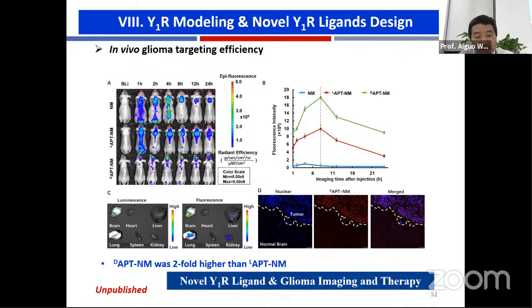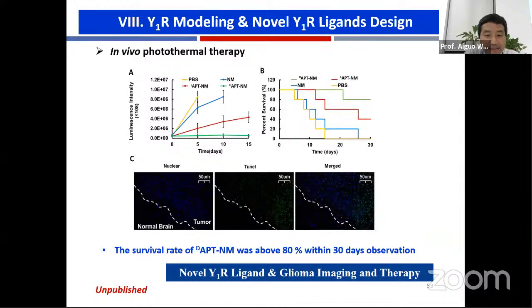And we found this is very interesting, the novel Y1 receptor ligand and the glioma imaging and the therapy. And also, we found the survival rate of the D-type APT nanoparticles was about 80% within 30 days observation for the mice.